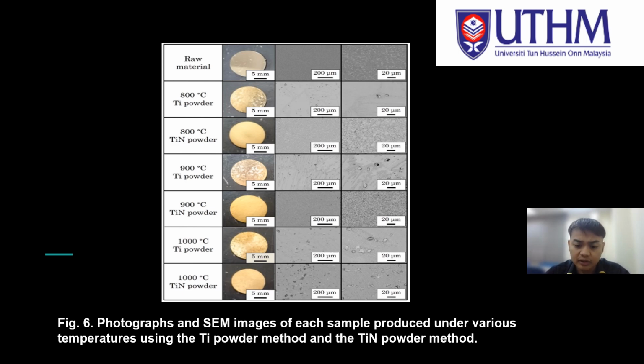As mentioned in the introduction, the TiN coating mechanism is thought to be due to thermal deposition or sputtering of the raw powders. In addition, there is a possibility of hot spots due to the strong electric field generated between the raw powders as the cause of the thermal runaway, and plasma generation due to this strong electric field is also considered to be possible.